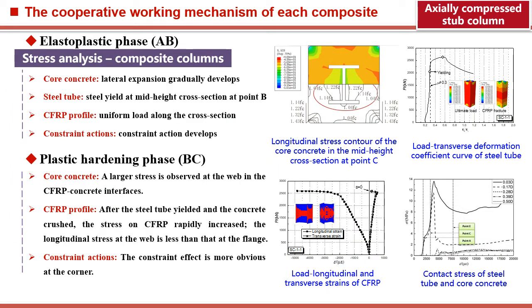However, in the elastoplastic stage and the plastic hardening stage, due to the longitudinal cracks and expansion of the core concrete, FRP profile and steel tube have double constraints on the core concrete. At the location of the profile and the corner of the cross-section, a very obvious restraint effect is observed, which significantly increases the stress of the concrete in the two areas.